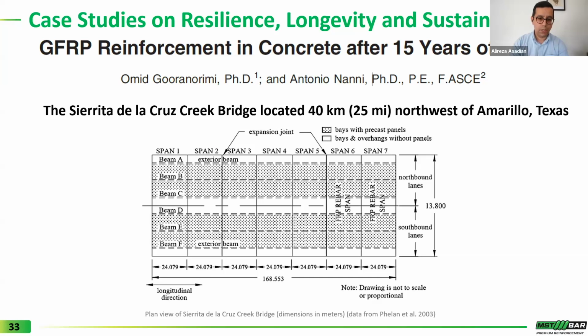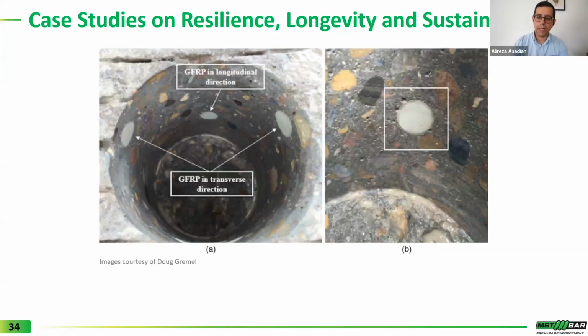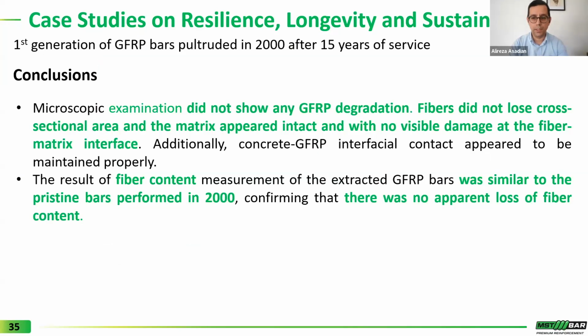Similar to the previous study, they did some core sampling in this study and did some microscopic analysis as well as some shear tests on the samples. And again, they concluded, similar to the previous project, that the microscopic examination did not show any GFRP degradation. Fiber did not lose any cross-sectional area, and the matrix appeared intact with no visible damage to the fiber matrix interface. The fiber content was similar to the pristine bar produced in 2000, confirming that there was no apparent loss of fiber content for the rebars